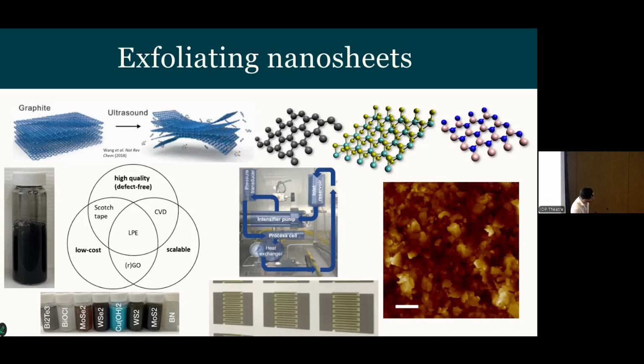We can also then, on all of these different size selective fractions, once we know the size, look at the surfactant content. So these are exfoliated in soap and water. It's notionally environmentally friendly processing. And we find that the samples that are smallest do indeed have more surfactant, more stabilizer, because they have more surface area, so that's what we expect. And I'll come back to that later.